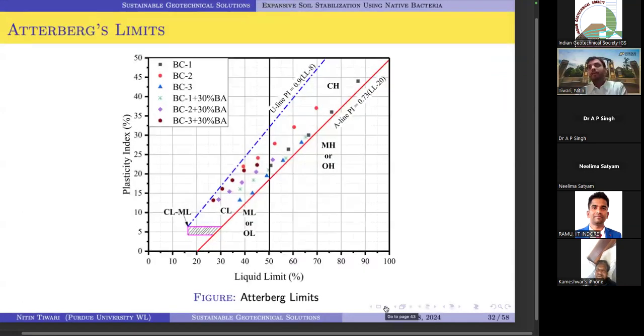Okay, so after treatment, as I mentioned, we did all kinds of Atterberg analysis, and we observed that initially our soil used to classify under the CH category, which is highly plastic clay, but with the treatment, most of the samples went to low plasticity clay. So it shows that ultimately we are changing the Atterberg limits, which is a positive indication for our treatment. At least on the plasticity side, it is working really well.